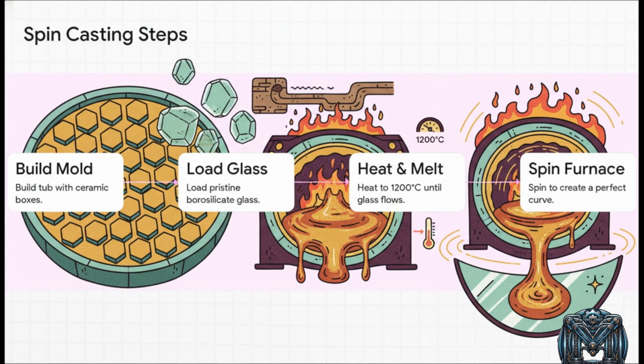They seal up the furnace and blast it to 1,200 degrees Celsius. The glass doesn't turn into a watery liquid, it actually reaches a consistency like thick, cold honey. Over a few hours, it slowly oozes down into the tiny 12-millimeter gaps between those 1,700 boxes, all while the whole furnace is spinning to give us that beautiful curve.